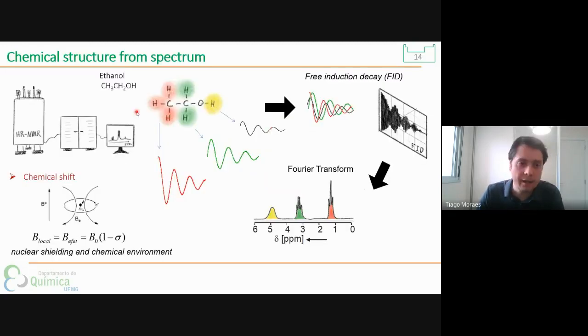Okay, so in high resolution NMR, what we have, for example, for ethanol here, is that the hydrogens in this molecule are not feeling the same effective magnetic field, but they are feeling different effective magnetic fields. So when we detect the signal of this sample and do the Fourier transform, we obtain a spectrum like this, where we can identify which peak represents each chemical environment of the sample, and from the fine structures of this spectrum also discover more about the chemical structure, right?